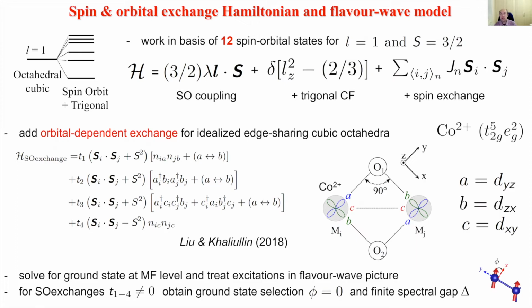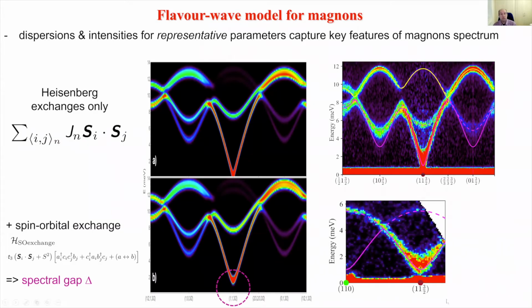And as a consequence, by calculating excitations of this in a generalized spin wave formalism, so-called flavor wave, one finds a gap. I'm illustrating here the results of the magnon dispersions if we put some representative values for these exchange interactions. So here, because this is a much more complex calculation, it's not possible to do the same type of comprehensive fitting and variation in phase space as we've done before. But by trialing a number of combinations of exchanges, we can find sets that produce dispersion relations that are similar in bandwidth to the magnon dispersions.